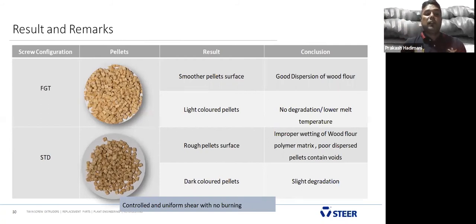And if you observe the standard technology, there is a rough pellet surface, and we also observed higher moisture content. More interestingly, the pellets were a little bit darker in color, and we observed slight degradation on the pellets. The wetting was very bad, improper wetting of the pellets, and poor dispersion of the wood powder into the polymer matrix. We also observed many voids and particles in the standard technology. It may be due to improper wetting of the fiber, and distribution and mixing.